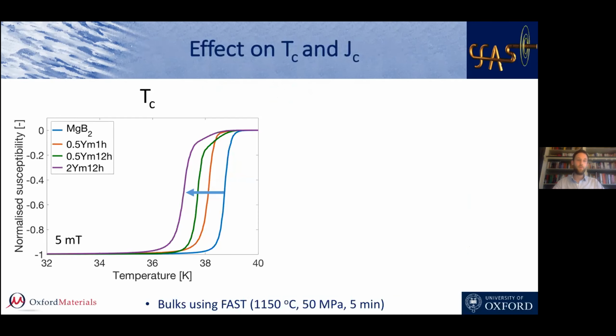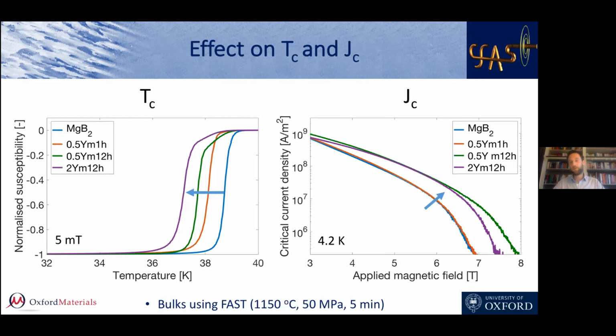And what it did on the properties, well, not so much on TC, which is good because we don't want to drop TC too much. So here we lost 1 or 2 Kelvin, which is quite minor. But the positive thing is that by having 0.5 or 2% yttria and by ball milling for long enough, so that means 12 hours, we can see that we shifted the curve, we pushed it upward and outward, which is exactly what we wanted to do, because it meant JC performance was improved with the new pinning centers.